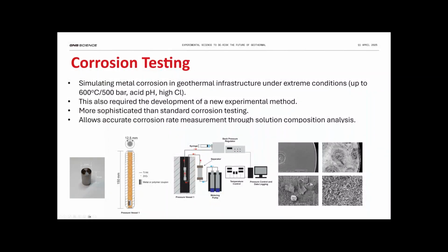That prevents the coupon from touching the walls of the titanium pressure vessel, because there could be galvanic corrosion. Now, in this case, because we're not looking at silica scaling, we only use one pressure vessel, and we pass the fluid through at whatever rate we think is the best for that corrosion test, and we measure the actual concentration of metals in the fluid coming out. So particularly iron, which is most indicative of corrosion. And so we can actually get a much more detailed and sophisticated measure of the corrosion rate.